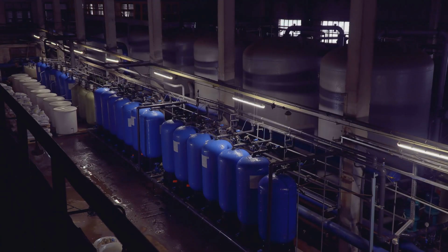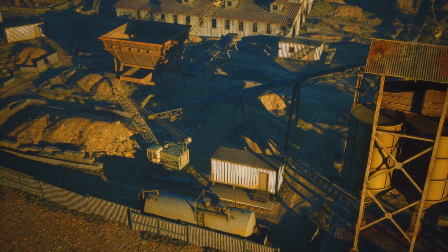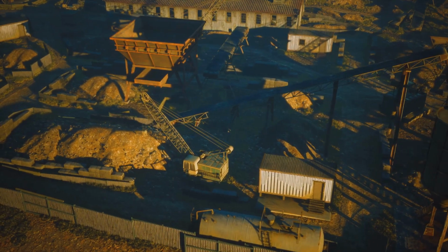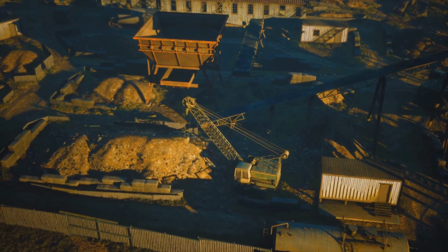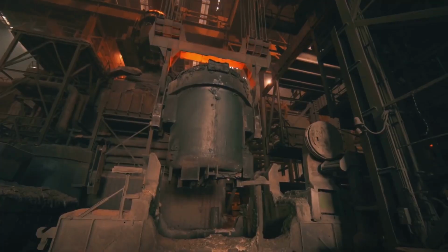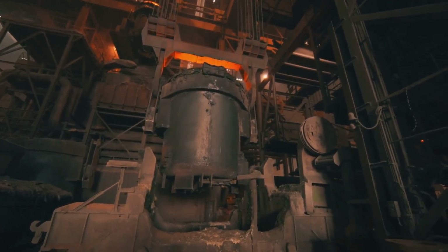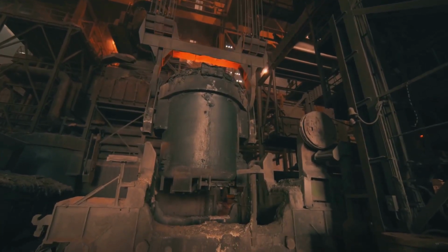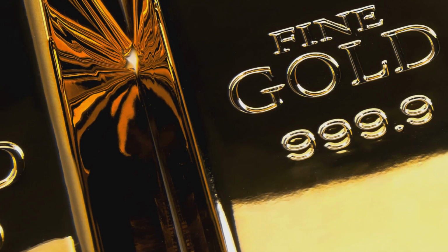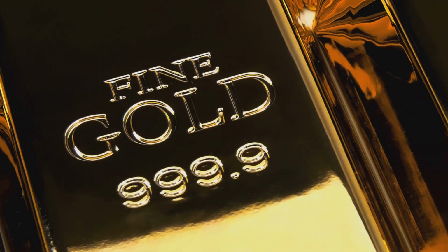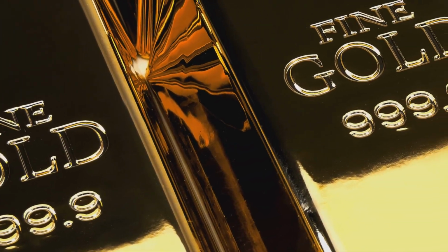Carbon in pulp. Activated carbon adsorbs the gold cyanide complex, then is screened out. Tailings are detoxified to neutralize cyanide before storage in a licensed facility. Gold is stripped from carbon in hot caustic solution. Barren carbon is reactivated and reused. A small volume now holds a high concentration of dissolved gold, ready for final recovery.